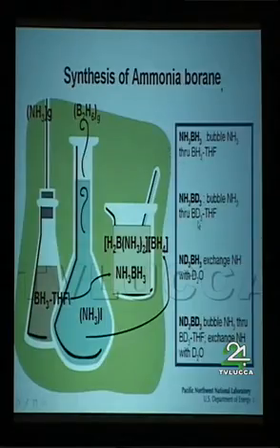And fortunately, you can buy deuterated boron THF and do the same process and get deuterium on your boron. You can put the deuterium on the nitrogen just by, it's very labile. You can exchange it with D2O washes, do that a few times and wash all the hydrogen out. And then the last one that we really want is for deuterated is just to start with the deuterated THF and then exchange that. So we have all 4 of these samples here now so that we can go through and see what the reactivity of these things are. So we need these for fingerprints for control experiments, but we're going to make an intimate mixture again of the ammonia borane and the per deuterated species.